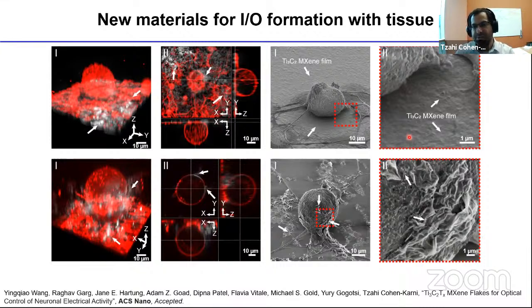You can make it a few centimeters across, or we can actually do flakes. This is what I mentioned before. So 2 nanometers in thickness, and they are on the order of a few microns to, let's say, 10 microns, give or take. It depends on the synthesis conditions. This was done in collaboration with Yuri Gogotsi at Drexel University. So you can see in this case, the MXene is attached to the cell membrane, and same idea, we shine pulses of laser and we can get cell actuation.